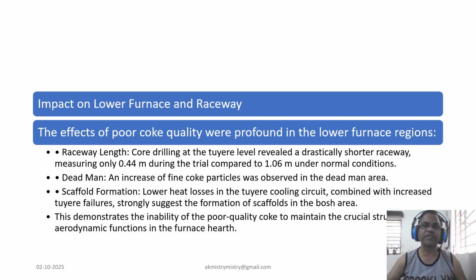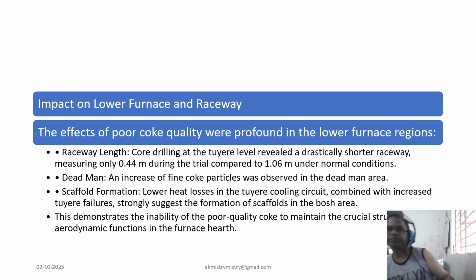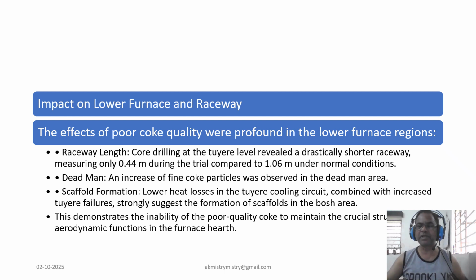The most dramatic physical evidence came from the lower furnace. Core drilling at the tuyere level was performed to measure the raceway, the cavity where combustion occurred. The results were, as the report says, extremely disappointing. The raceway length was found to be just 0.44 meters during the trial. For comparison, under normal conditions, it measured 1.06 meters, more than double the length. This drastically shortened raceway, along with an increase in fine coke particles in the dead man and evidence of scaffold formation, proves that the poor quality coke was breaking down and could not maintain the essential structure and gas flow in the heart of the furnace.